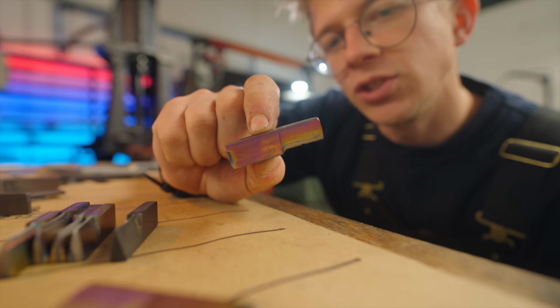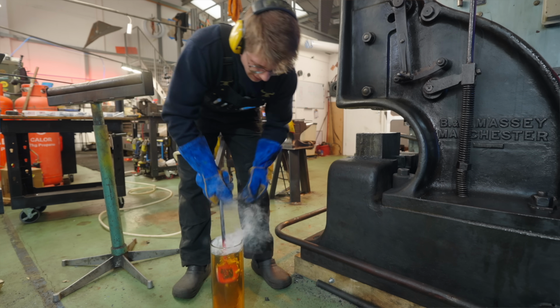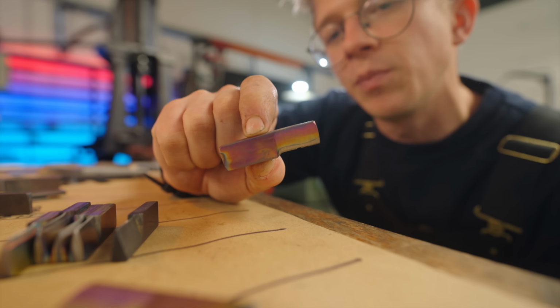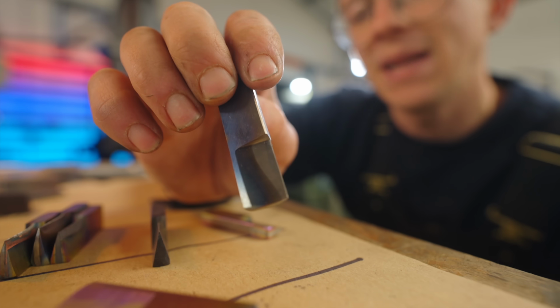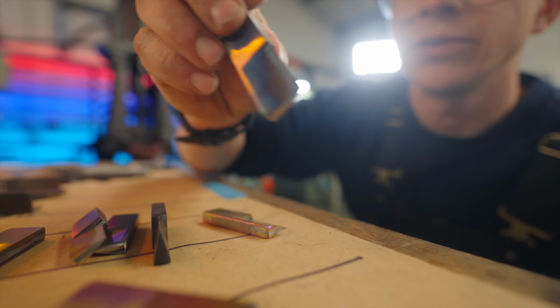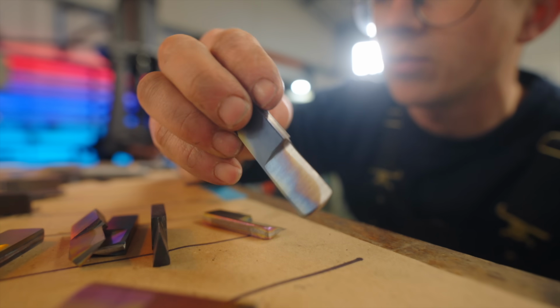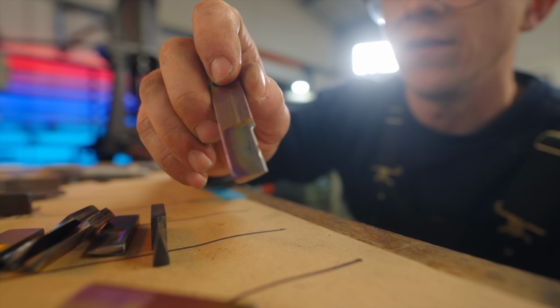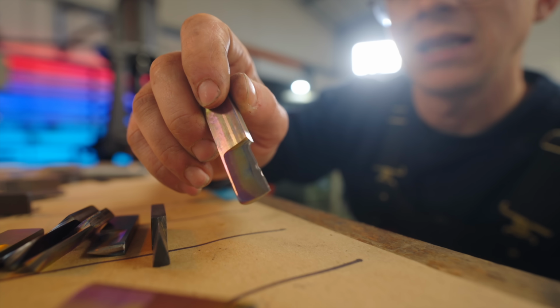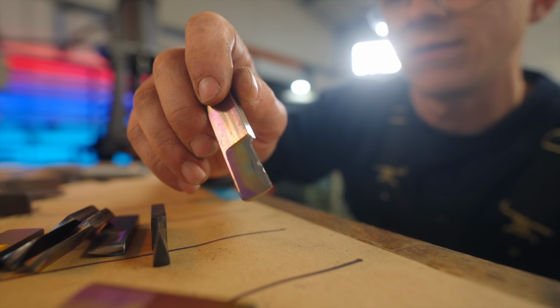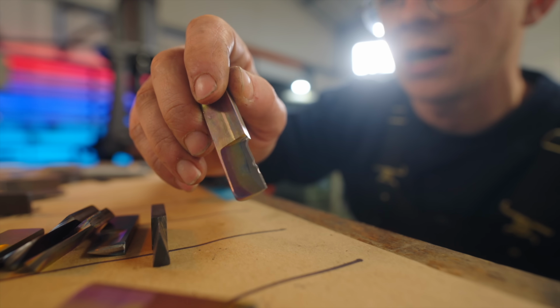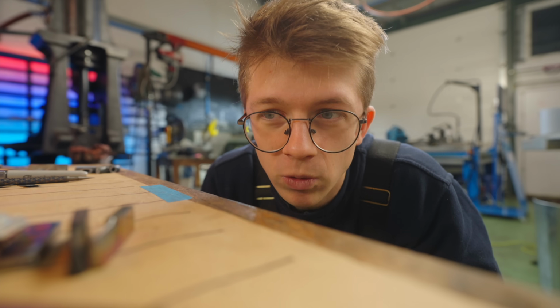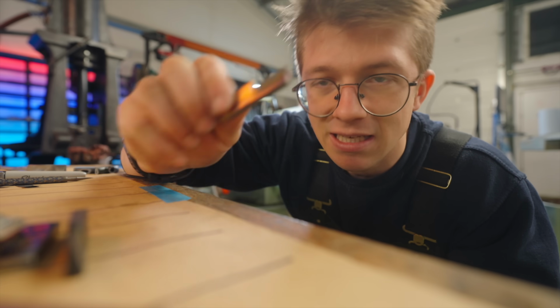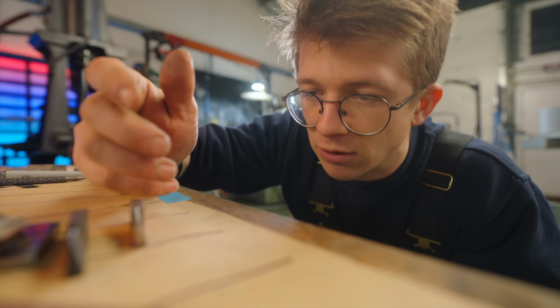However, this was quenched when it was in a big block that it was then subsequently water jet cut out of. So potentially, the material that became the edge on these samples was able to cool quick enough to harden properly, and the material that became the edge on this sample, because it was stuck inside that big billet, did not cool fast enough, and therefore did not reach as high a hardness, causing the edge roll. I just need a Rockwell hardness tester. Is this actually softer? And then with the numbers, we then got to refine the process.